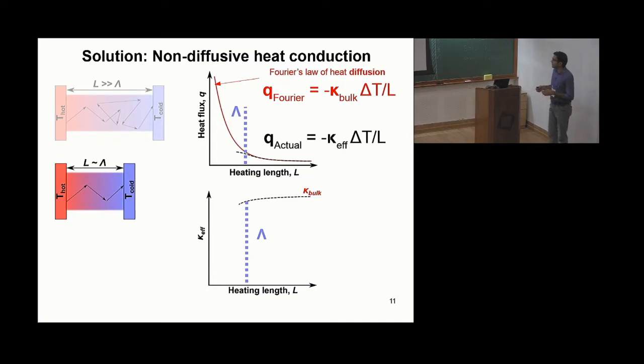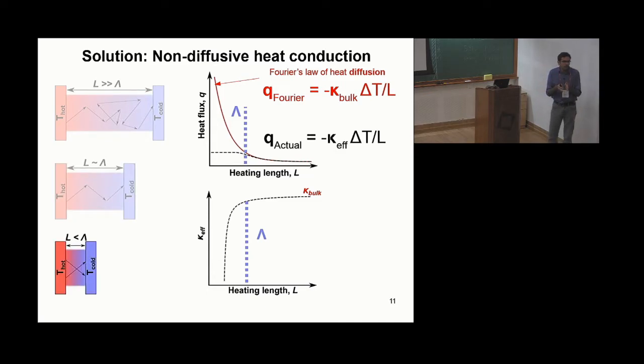In the limit where the hot and cold ends are very close together, such that L is much smaller than lambda, the heat flux actually saturates to a constant value, but L goes to 0, so the effective thermal conductivity should also go to 0 for the equation to be valid. So this regime where there is no scattering possible, or very few scattering events possible, is not a diffusion regime, but is actually called quasi-ballistic, because it is somewhere in between fully ballistic and fully diffusive. It's called the quasi-ballistic regime by convention.